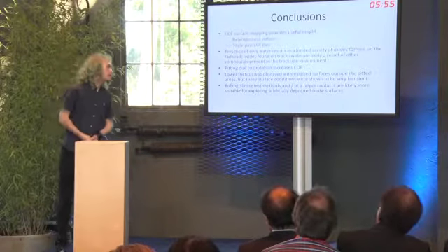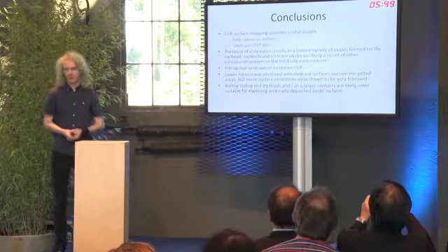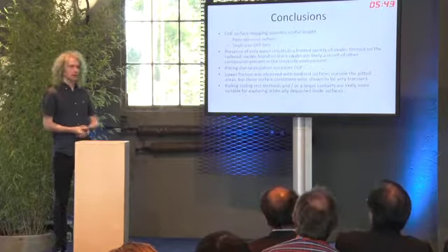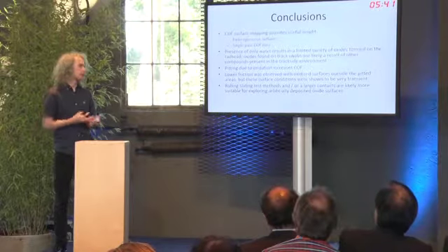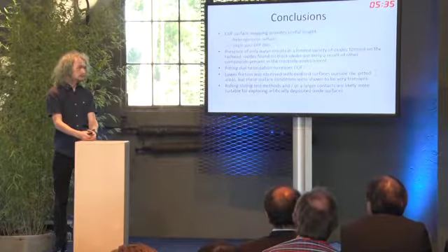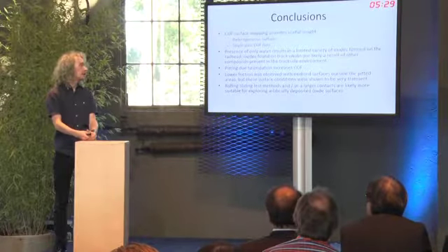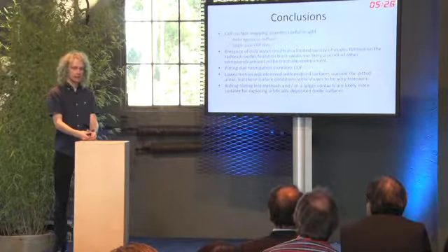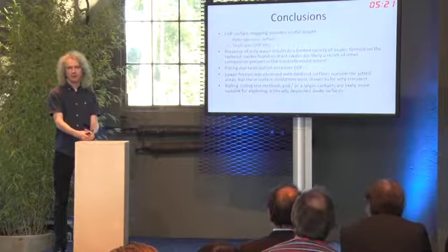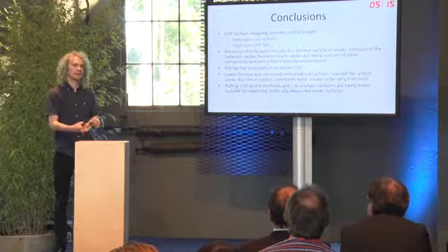So to bring all this together, the COF surface mapping actually produces some quite interesting and useful insight into these contacts. We can actually see what the individual areas which a non-homogeneous surface is producing. So where the oxide is causing the friction to increase and where it's causing it to lower down. And it also allows us to basically run a single pass over a surface, whereas it wouldn't be possible, for instance, in the twin disk testing, because you're continuously rolling over the same surface and it's removing what has already been there.